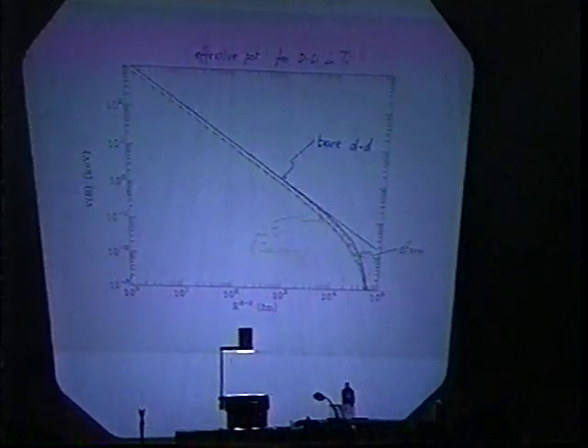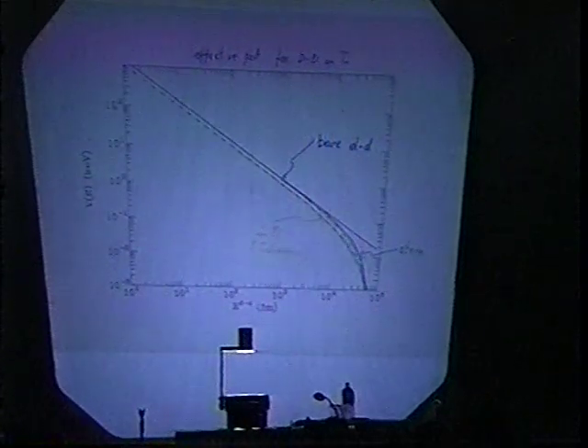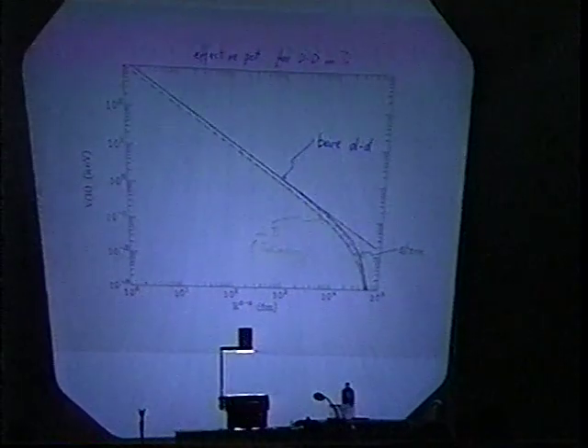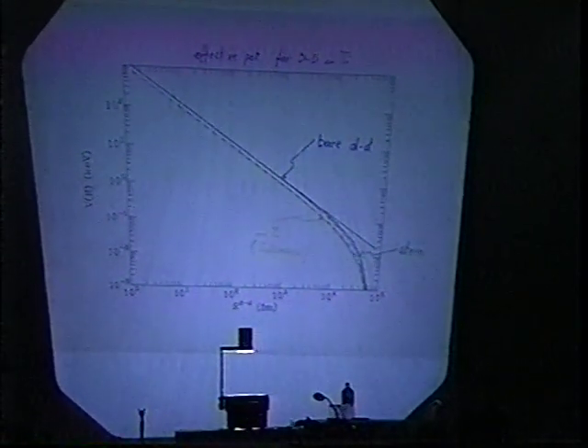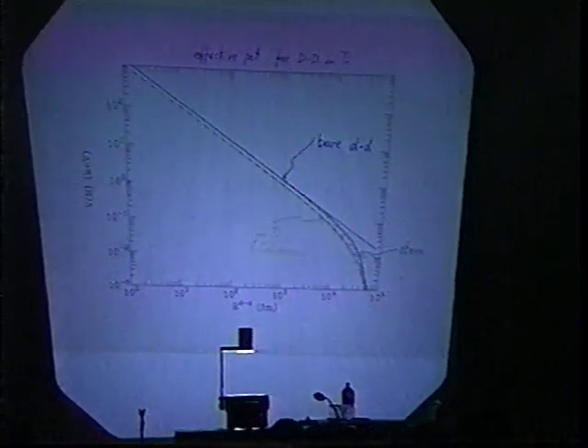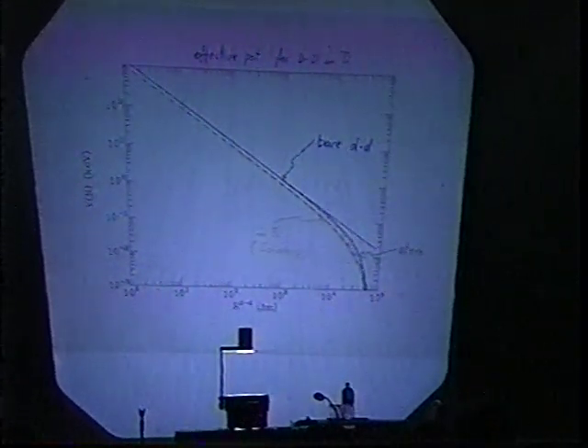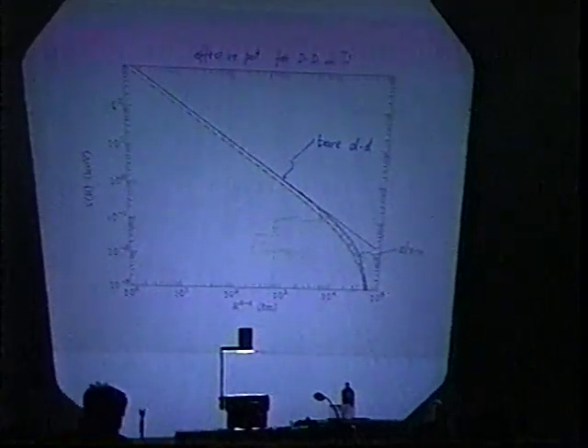In the metal case, of course, there is no accurate measurement, but what we expected is something like this potential. This is the effective potential for D plus D in titanium calculated by Ichimaru some years ago. And here is the bare D-D potential, just a Coulomb potential. For the atom case, of course, we can see the electron shielding effect here, with something lower in this region. And in metal, according to Ichimaru's calculation, we have a reduction of the Coulomb potential. I calculated the effective screening potential, which is something around 50 electron volts for the titanium case.